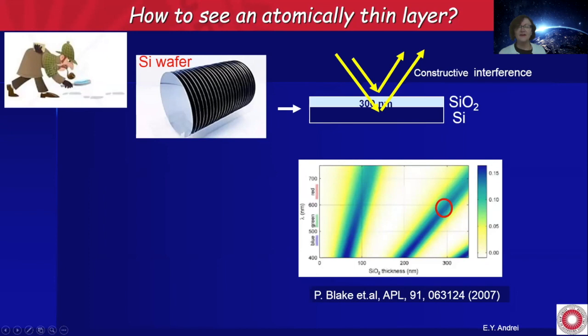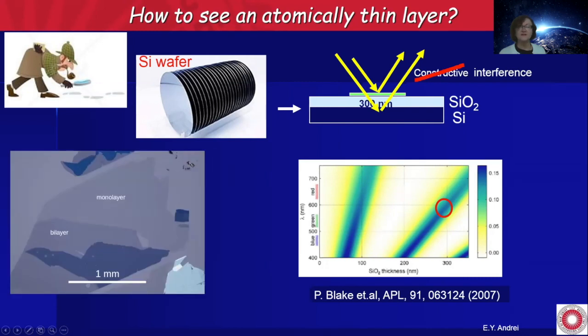So what we have here is a constructive interference between light that reflects from the bottom layer, the silicon dioxide interface, and the light that reflects from the top layer. If you have the right thickness and the right frequency, there are points of constructive interference. In this particular case, the silicon dioxide was about 300 nanometers thick, and it was designed to have constructive interference for green light, the frequency that our eyes are most sensitive to. Now, if you have a speck of dust falling on it, the constructive interference is destroyed, and that gives rise to this shadow.